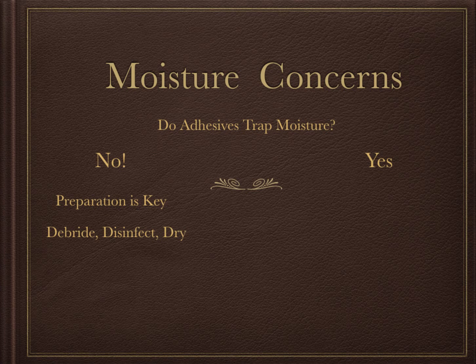Drying is the number one step for every adhesive application, even on the wall, which can be fairly impervious to wet. You still have to dry it. We use a heat gun or a propane torch to accomplish that. If you do all that, an adhesive application can actually help maintain moisture balance in the foot by not having exposed sections. Like I said, with a big resection, moisture is evaporating off that foot, so it's drying out, unless it happens to be standing in mud.